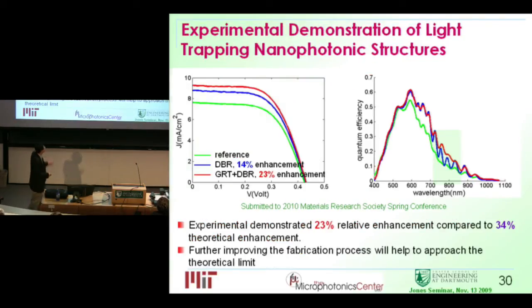So this is a preliminary experimental result. With DBR, we demonstrate 14% enhancement. This is the IV curve, except that I'm flipping over the fourth quadrant because people want to see positive things for good. That's how the solar industry uses this kind of chart. DBR plus grating, what we call textured photonic crystal structure, gets 23% versus the theoretical ideal 34%. And this residual part should be able to improve with better fabrication process. And if you look at the absorption spectrum, you do see a significant enhancement in the infrared range compared to the reference sample. That confirmed our light trapping scheme.